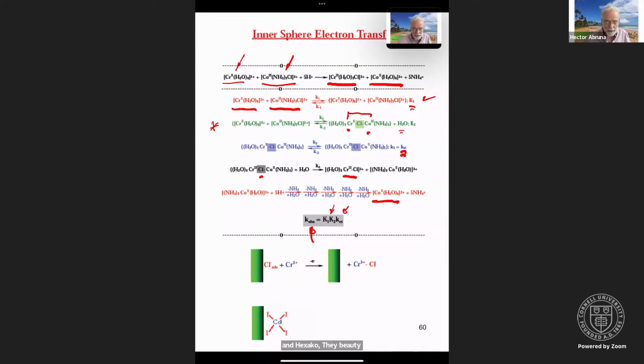The beauty of this experiment, and it's one of the nicest, this was in the 50s, where instrumentation was like a spectrophotometer and a battery. But the design is what's really amazing. There's no other way that you can get those products without having an intermediate that is sharing the chloride as a bridging ligand, because you have the net transfer of the chloride from this guy to this guy. As you can see, the chloride goes from the cobalt to the chromium. And so that was probably the first clear experimental observation.